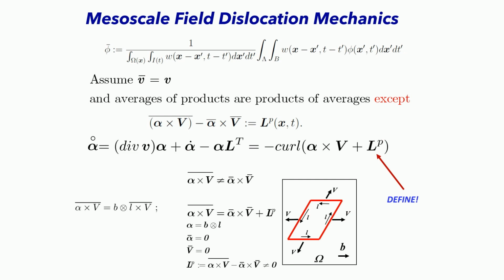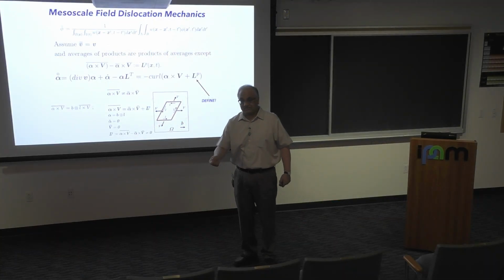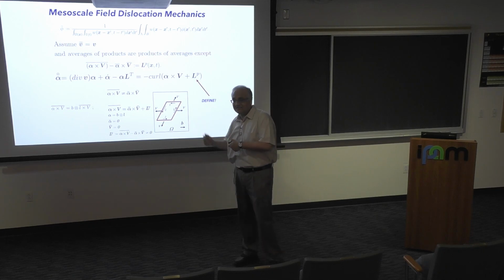And when you do that in this sort of situation, under some assumption, so basically there was a curl of alpha cross V, you have to average that in the microscopic theory. Most of the time, the compensated compactness magic is not going to happen. Here, you can even explain physically why the average of the products cannot be the product of the averages. So a piece is going to come out, which is the difference between the mean of the product of two terms and the product of the averages. And this is what engineers actually feed in with constitutive assumptions, and for good reason. This is hard, as you can see from the structure.